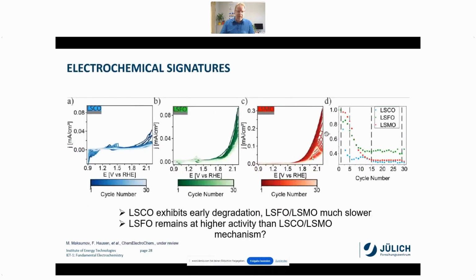And what you can see in the electrochemical signatures, these are cyclic voltammograms recorded in the electrochemical AFM cell. So they are not as perfect as you would expect them to be if you would record them in a proper or in a real electrochemical setup. So they are not as good, but the important features are all there. And what you can see here is the current density versus the potential. So you see already we go to much higher potentials than we would like to go to. And you see also here the number of cycles. So if you cycle from 1 to 30 cycles, they are decaying the current density. So the material is degrading drastically.